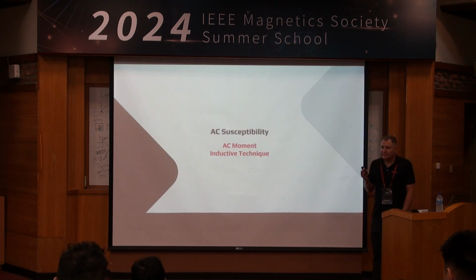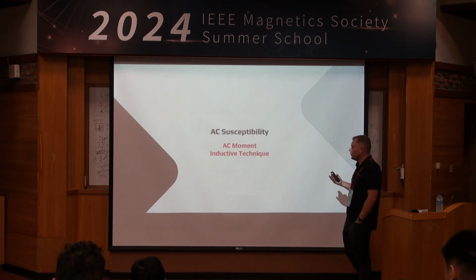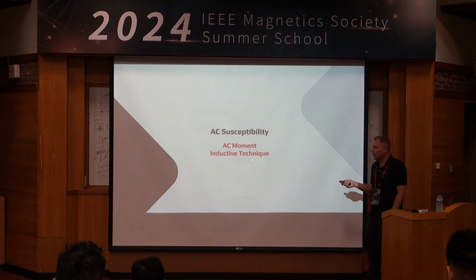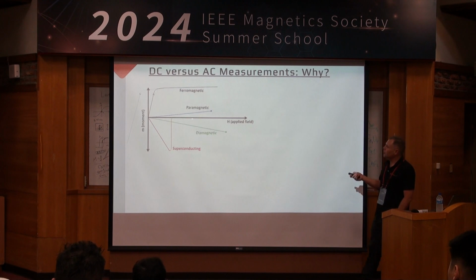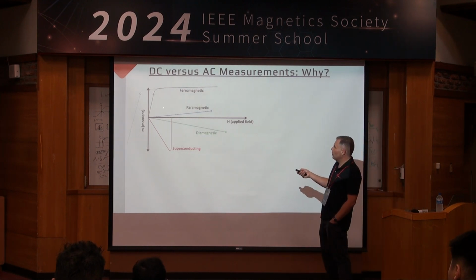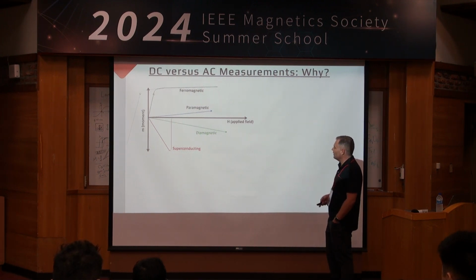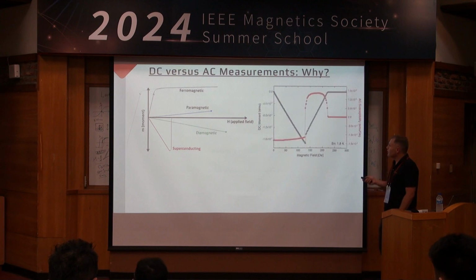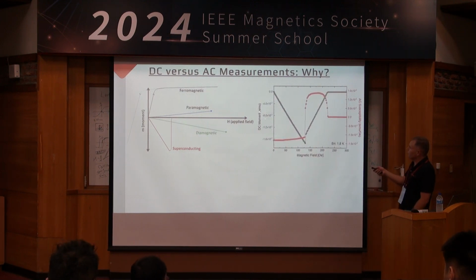AC susceptibility. Pick it up a notch with frequency. AC moment, again, we're still in the realm of an inductive technique here. Here I show some examples of just DC moments: paramagnet, diamagnet, superconducting, like the Meissner effect, and then we kill the superconductivity, something ferromagnetic here. Here's an example of a superconducting sample, the DC moment shown in black. So again, this is like this data here. And then as we increase the magnetic field, we kill the superconductivity.